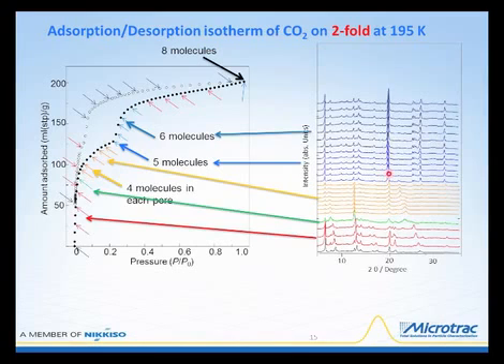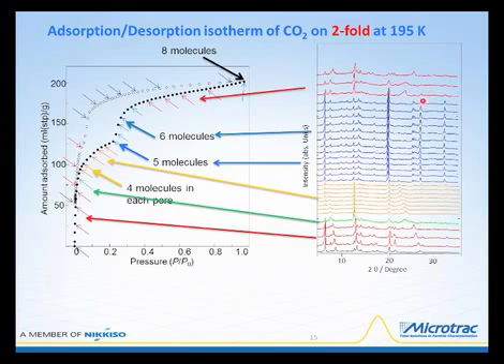And then we can continue the process, and as more and more CO2 molecules are being accepted into the cage-like structure of the MOF, and then we continue further, and we start to see even more changes that are occurring as the relative pressure is starting to achieve saturation, and more molecules along the line here. We're starting to approach somewhere between 6 and 8 molecules per pore. And then finally, as we reach saturation, we have 8 molecules of CO2 per pore. So we're able to track everything that's happening and the structural changes that are occurring throughout the entire process of adsorption.